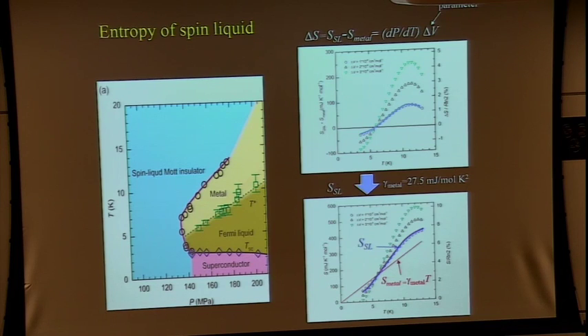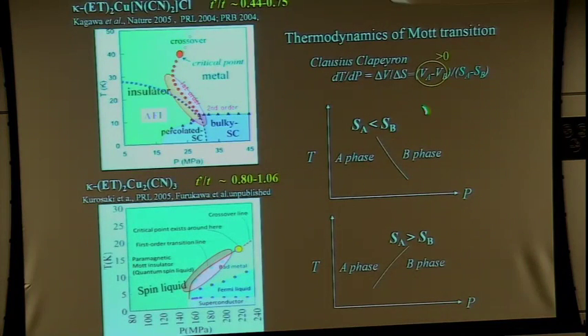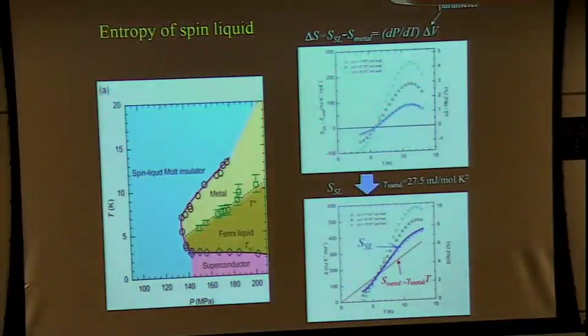So from this slope, by using these relations, you can get the entropy difference as a function of temperature. You see, around 6 or 7 kelvins, the entropy balance is reversed. At higher temperatures, the spin entropy of the spin liquid is higher than the Fermi liquid. However, below these temperatures, the entropy of the spin liquid is smaller than this metallic Fermi liquid. So it may suggest that some less entropy state is stabilized at low temperatures.